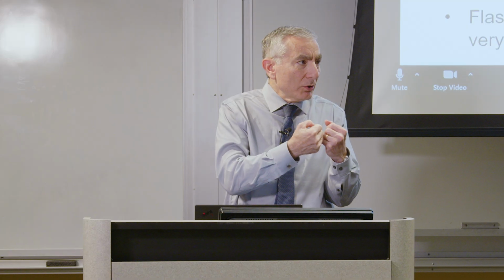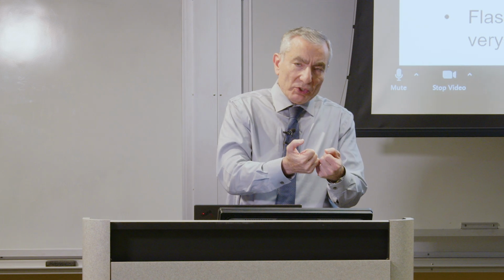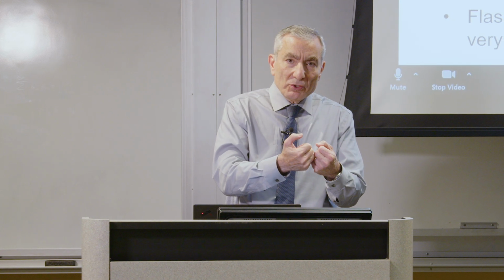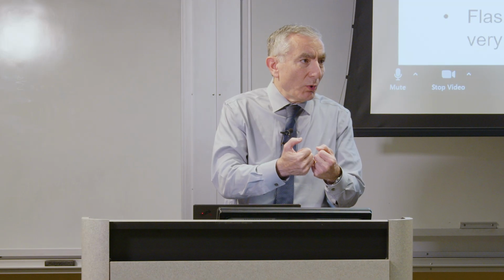So we're going to put a powder in there, and so you're going to have these powder particles. At these points where it's touching, there's a little bit of resistance at these points as these are touching, and it's those that are going to generate the hot spots, and this is going to get hot really fast.